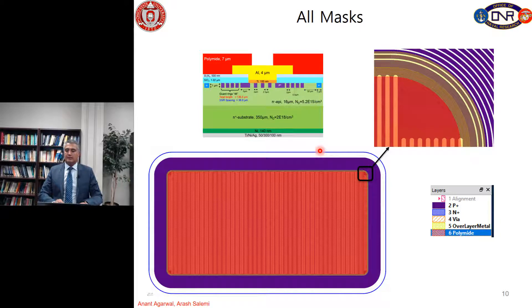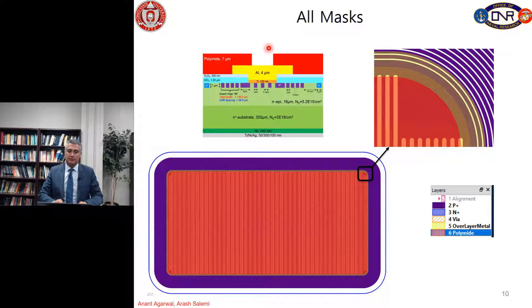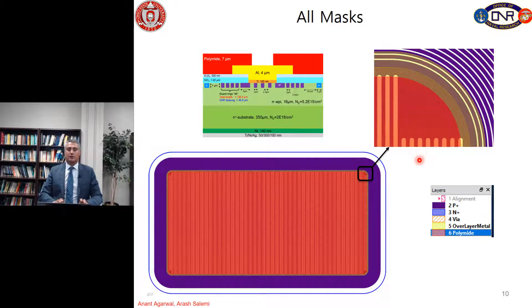Finally, mask number 6 is the polyimide. Polyimide acts as a dielectric for the packaging. We coat the sample with 7 micrometers of polyimide and then use a proper mask to etch the middle part to reach the overlayer metal. We need a rectangle at the center of the active area with rounded corners again. Here are all the masks needed for fabricating these devices.